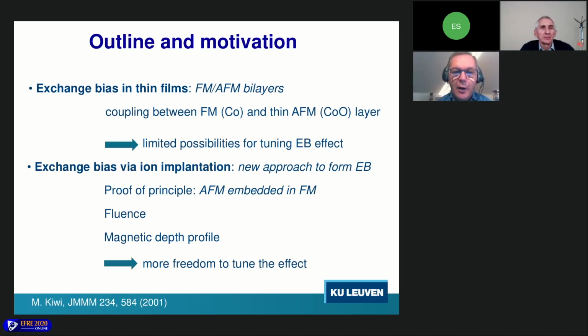And so it has been our aim to try another approach, namely not to use natural oxidation of cobalt, but rather to create the cobalt oxide by doing implantation of oxygen ions into a cobalt layer. In this way, we want to see if we can modify the magnetic properties of the layer.